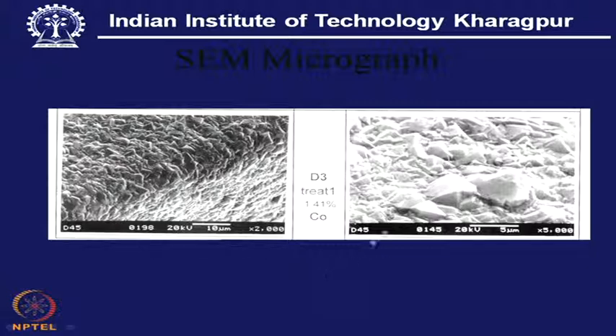Now, here one weakness or fault in the coating is also identified. So, this is a nice coating deposition which is recognized by SEM, but this is at the same time also a fault with the coating. What we can see, the remaining part of the coating is more or less uniform, that means the crystal size is more or less uniform, and that is one of the requirements we mentioned at the very beginning of the lecture. But here what we have seen, unfortunately, is a too large crystal.